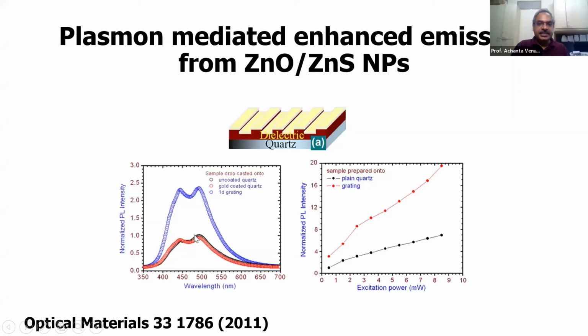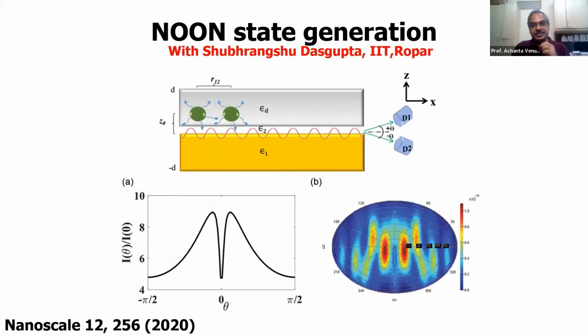Right. So what we see, comparing the unpatterned metal region and the patterned metal region, is almost 2.5 times enhancement in the emission from these nanoparticles. This is Purcell enhancement, the weak coupling example, where the emission from quantum dots can be enhanced because of the strong local field excited at the metal-air and metal-dielectric interfaces. When the plasmon is excited, you have a strong local field which confines the light to nano dimensions or the interfacial dimensions.